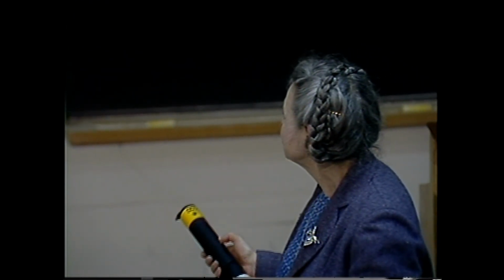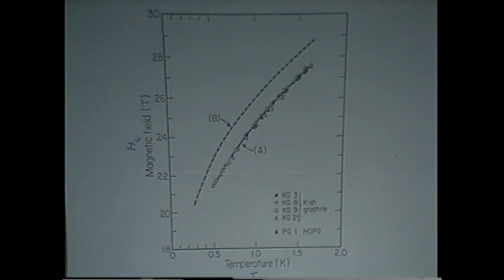And here's the anomaly, you see. It happens at high fields, close to 25 Tesla. And it is not a one-electron phenomenon. Why isn't it a one-electron phenomenon? Because one-electron phenomena don't have much of a temperature dependence, but this thing has a big temperature dependence. And here's the magnetic field where the anomaly occurs as a function of temperature, and it has quite a wide range of field dependence. And in fact, the functional form is a BCS type form.